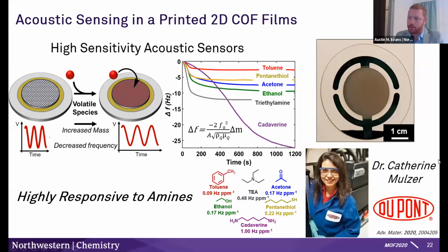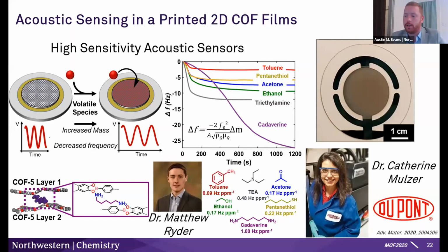And this cadaverine adsorption really, really confused us at first, but then we started thinking, well, maybe this cadaverine is binding differently than the other materials. And so my computational colleague, Matthew Ryder, who's now at Oak Ridge National Lab, looked into this using DFT and sort of validated what you might imagine just ad hoc, that perhaps this cadaverine is just the right length to bridge two boron sites. And indeed, we actually can see that in DFT, and as another set of circumstantial evidence, we don't see this unusual binding profile when we use COFs with larger pores, larger separations between the boron sites.